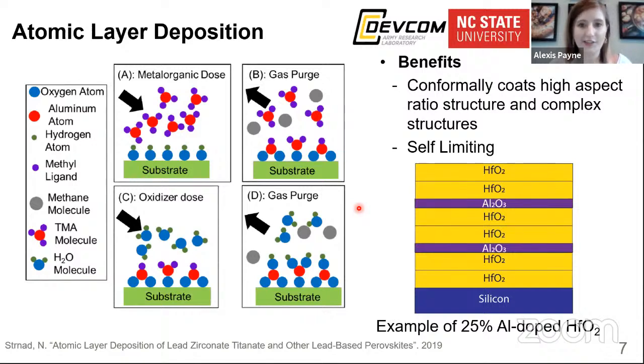These precursors are let into the growth chamber one at a time. And when they're let in, they saturate the surface, forming a monolayer of material. And the benefit of only growing one monolayer at a time is that you can coat really complex structures, high aspect ratio complex structures, such as our metal foams, which you can't do with other thin film deposition techniques.